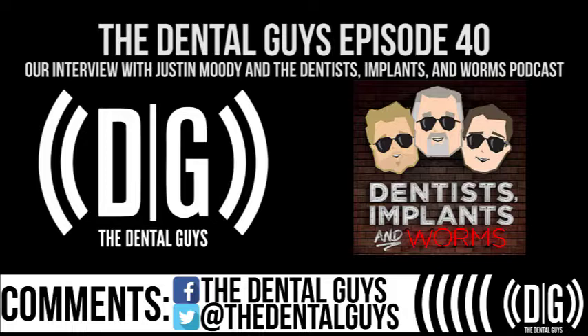Have I lost some arches from implant failure? Yeah, I'm not saying I'm 100% success rate, I'm just saying that hasn't been your problem. Last year on zirconia I had one screw-retained debond, and when I look back at it, it was an immediate molar. I chose one root over the other and had a little bit of a cantilever to one side. That's what broke the bond. It was me, it wasn't the material. It was restorative, because I put it in a biomechanically compromised position, and that's how it failed.